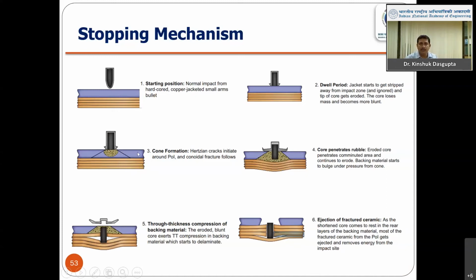Now these fragmented ceramics have taken the energy of the bullet but got fragmented themselves, and the fragmented bullets must be able to be stopped by the backing. For this backing polymer we have used carbon nanotube as well as ultra high molecular weight polyethylene. Initially a few layers of these polymers get torn up and finally the bullet is captured.